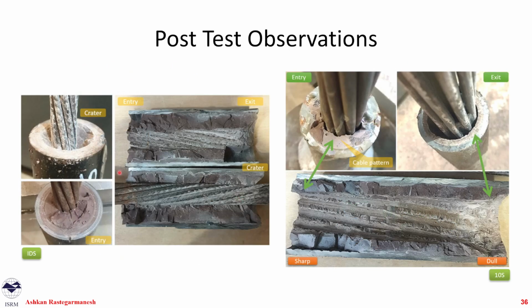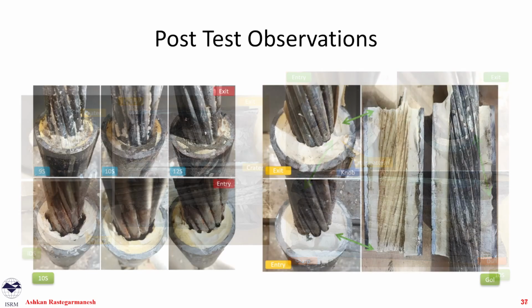Post-test observations: as you can see, in the smaller scale test, we get a crater at our exit point. So this is on the top. And on the bottom point, we get a little bit of mismatching between the cables and the lugs that the cables were initially cast into. And we see the damage, again similar to larger scale, on the right section, which is our exit point. Basically, we get a crater and much more damage. And as we go towards the bottom section, we see less damage.